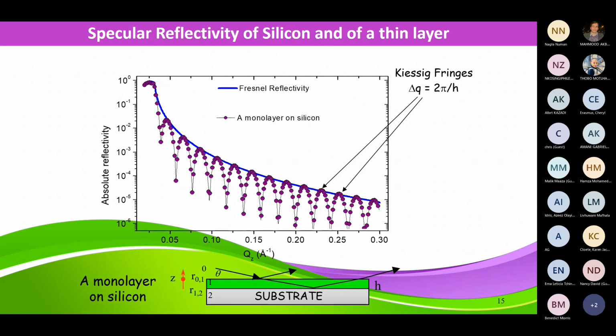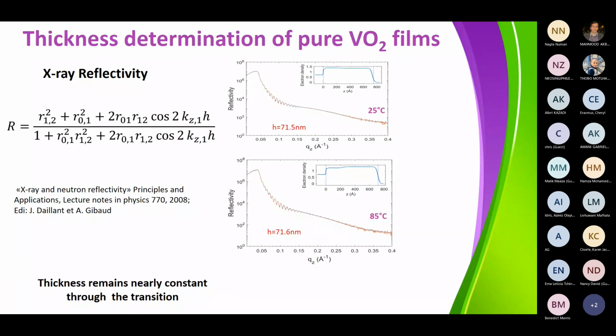And so if you look at that, if you have a large thickness, the fringes are going to be very next to each other. But if you have a very small thickness, the fringes are going to be very much separated. Okay? So this is a story about reflectivity. You can calculate this very well, and that's what we did here. And you can see that if you look at 25 degrees, what is the reflectivity of the film, you see very well the Kiessig fringes.